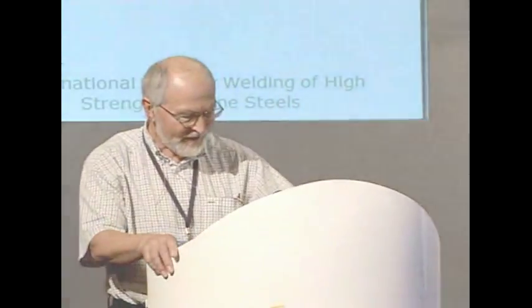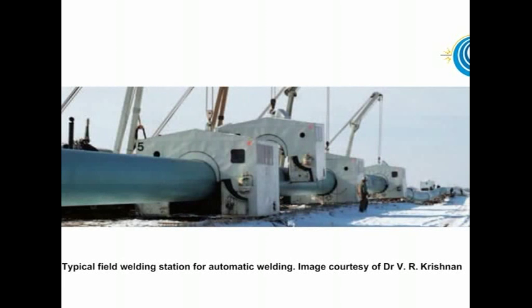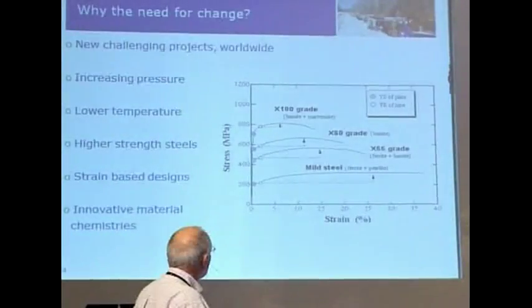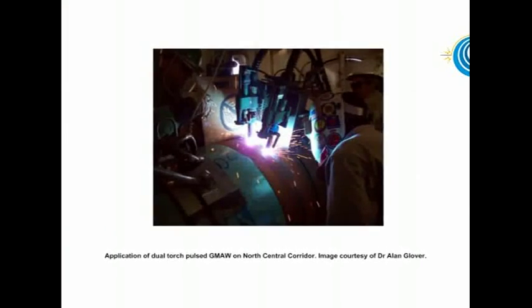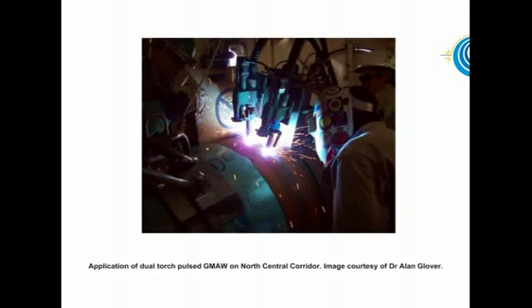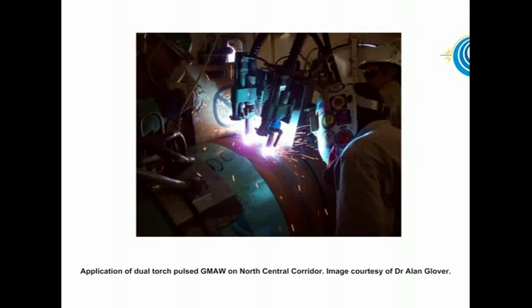In papers by consultants Drs. Glover and Krishnan, the relative costs of pipe material and construction were explored. Depending on the specific project, material costs can account for between 25 and 40% of overall project costs. But in Dr. Krishnan's experience, pipe construction costs are dominant and can easily be up to $1.5 million per mile of completed pipe. These factors together support the drive towards higher strength pipe, such as X80, and reduced wall thicknesses to reduce the volume of weld metal required in the field and permit installation in the fastest possible time using high-productivity multi-arc GMAW processes.